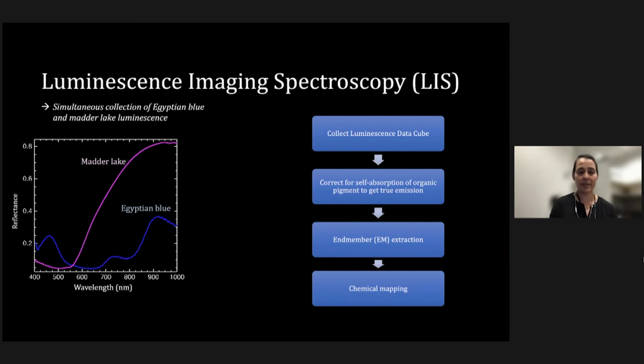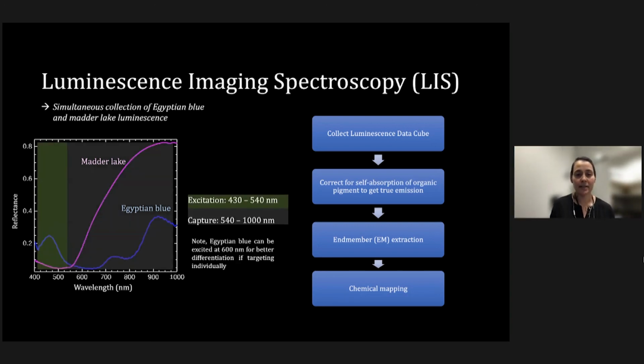So with luminescence imaging spectroscopy, we actually took an interesting approach here. Because Madder Lake also luminesces, we decided to excite both of these pigments at the exact same time. And because we're recording luminescence signatures and getting the entire spectral profile, and we know Madder Lake and Egyptian blue luminesce in different spectral ranges, we can record them at the same time and separate them. So we do that by exciting from 430 to 540 nanometers, and then filtering above 540 nanometers to capture both of their emission. So when we collect the data, we have to pre-process the data and correct some of the self-absorption of Madder Lake. We have to then data mine the cubes to find the signatures so we can do chemical mapping.